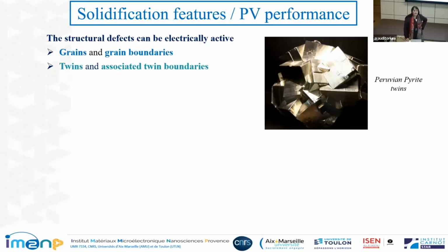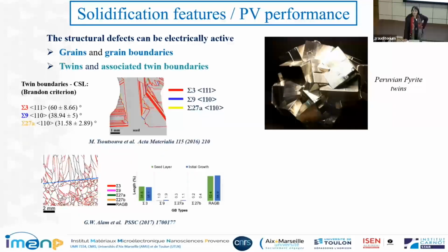Twins are grains with a very specific crystallographic orientation relationship. And you have an example here, not on silicon, but where you can see how it looks in natural minerals, in a pyrite mineral. And it's very frequent in silicon when you solidify it that you have different types of twins. The most frequent one is a sigma 3 one. It's a 60-degree rotation around the 111 crystallographic axis. And it appears in model samples. This one is one of our model samples, but also in industrial ingots.